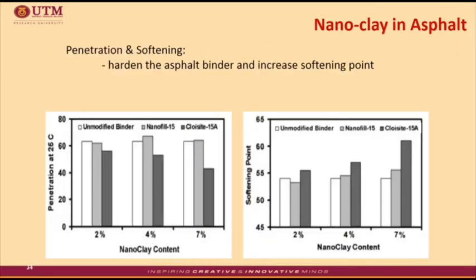Next, we have the results of penetration and softening point. Two types of nano clay were compared with unmodified binder, with nano clay content of 2%, 4%, and 7% by weight of the binder. Overall, it shows that the addition of nano clay hardened the asphalt binder and increased the softening point, which shows that it can stand higher temperature before it starts to flow.